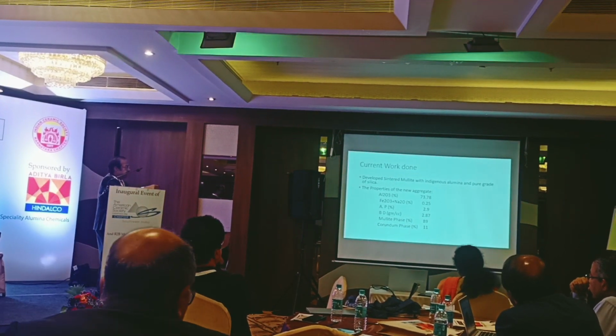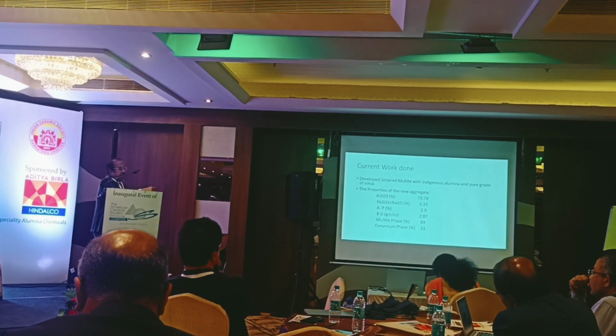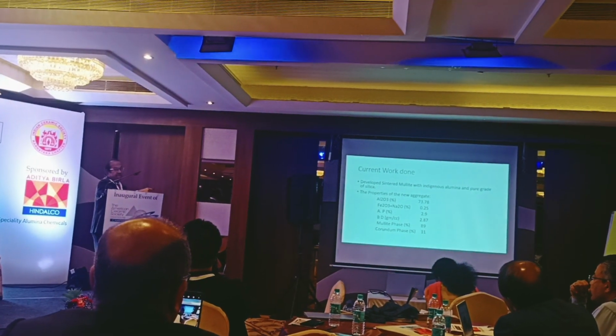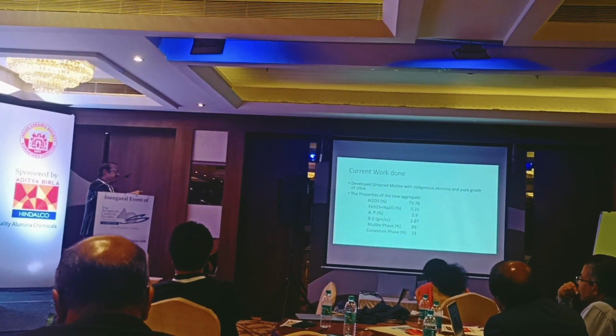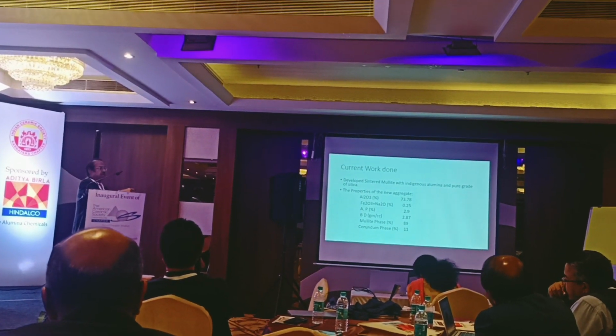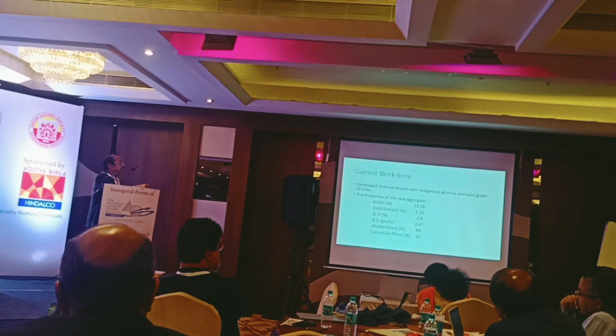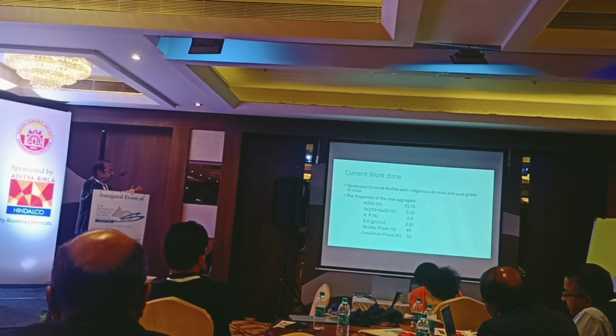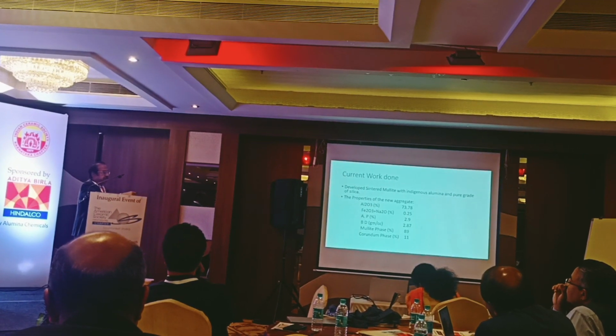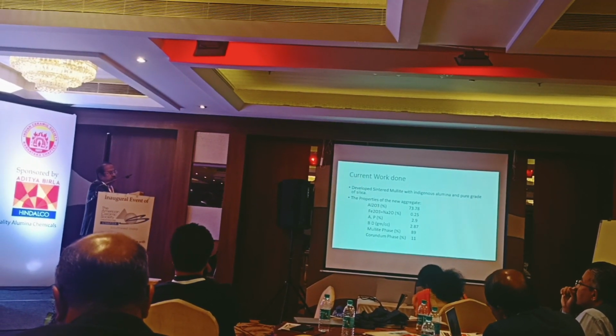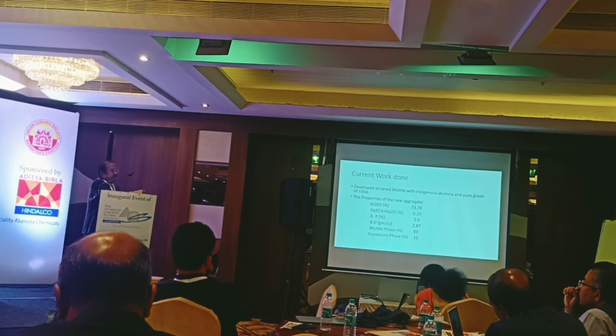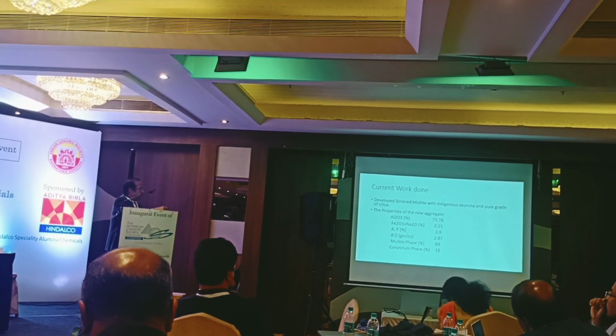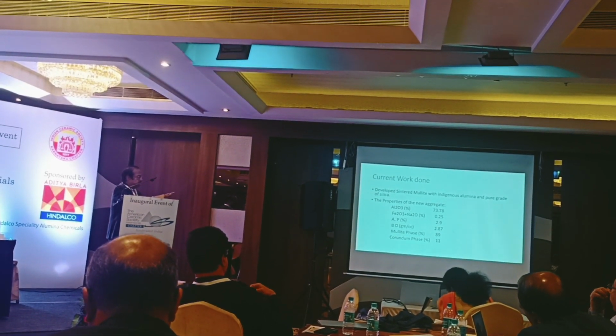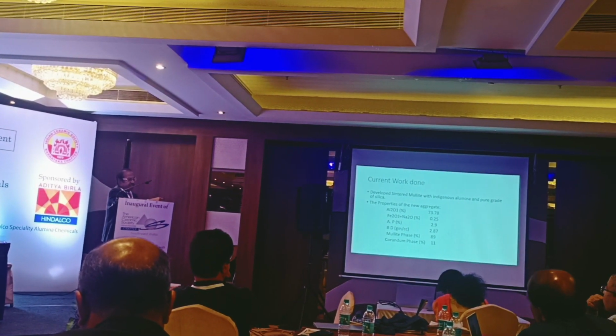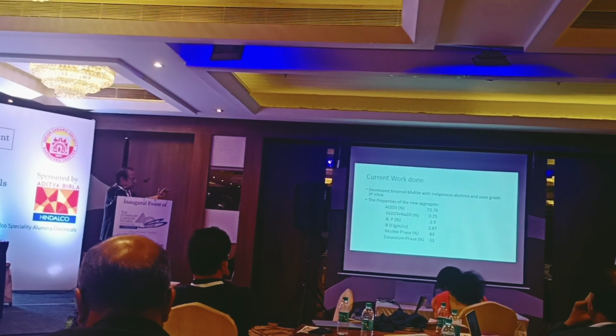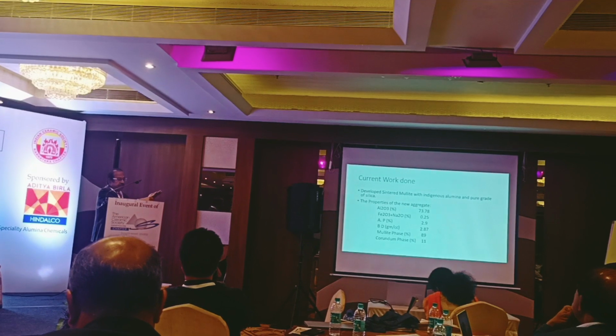Here you can see the impurity is 0.25% only. This is because we have started with calcined alumina. If we start with, say, reactive alumina or 99.8% alumina, the impurity will further come down. The porosity here is 2.9% because that is an acceptable limit, but it is possible to get maybe 0.1 or 0.2% porosity also. That product will be equal to pure mullite. And the mullite phase here is 89%, because we have added more alumina, because we don't want any free silica in the body. If we control the corundum phase, we can increase the mullite phase further.